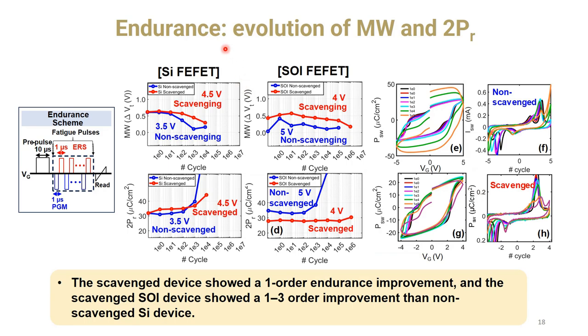And we also measured the endurance. From the endurance perspective, silicon and SOI FEFET are slightly different. First, for the scavenging device, the perspective is similar between the silicon and SOI. There is a one-order or higher endurance benefit if we use the scavenging technique. So in the SOI FET, the endurance is 1E6 and the non-scavenging device is 1E5. And the same thing happened in the silicon FET.